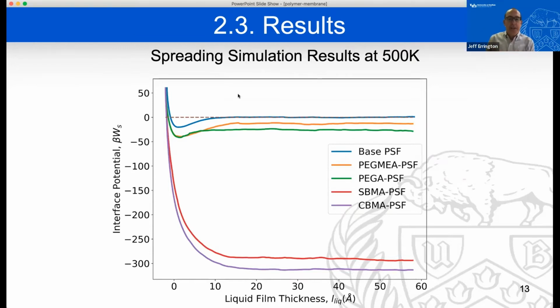We started the calculations at 500 Kelvin, and then as I'll explain in a moment, we went through a process in which we explored the free energies of the system down to room temperature. The reason why we start at 500 Kelvin is that it's simply easier to sample the system at these elevated temperatures in order to do the direct calculations, and then we use other methods to drill down to lower temperatures. So it's done essentially from an efficiency perspective.